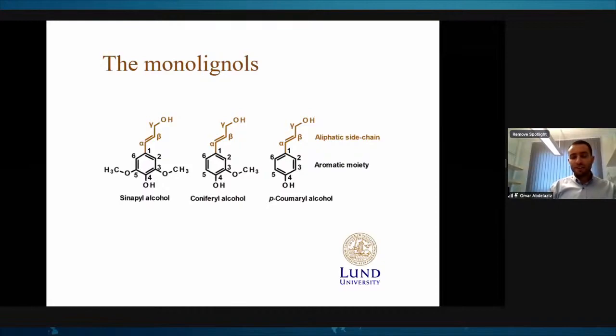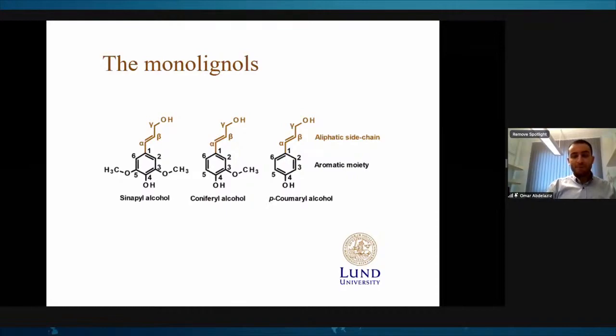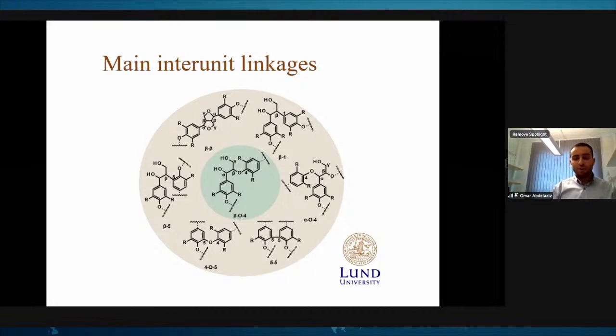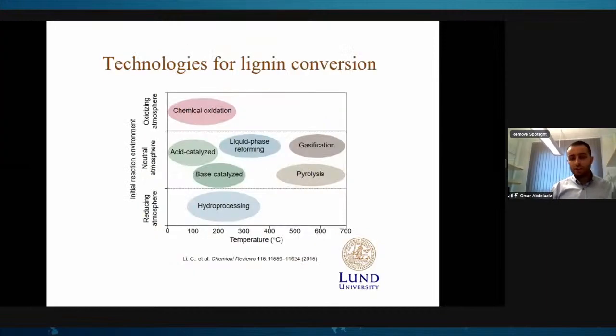I will be talking about lignin modifications and degradation. Before doing that, it feels classical to start with those hydroxycinnamyl alcohols — sinapyl alcohol, coniferyl alcohol, and para-coumaryl alcohol — the termed monolignols, which form the primary structure and through oxidative radical polymerizations form this complex 3D polymer. It happens in a random way, and it's connected by different linkages — mostly the aryl ether bond linkages and carbon-carbon bridges. The highlighted beta-O-4 is the most dominant, with quoted values between 50 to 60%, depending on the botanical origin — hardwood, softwood, or grasses.